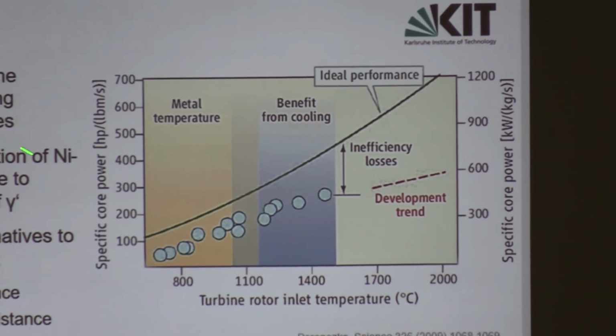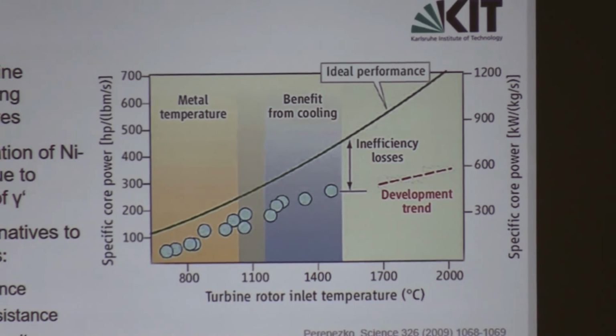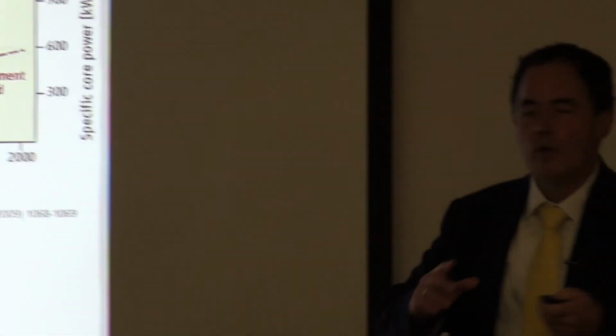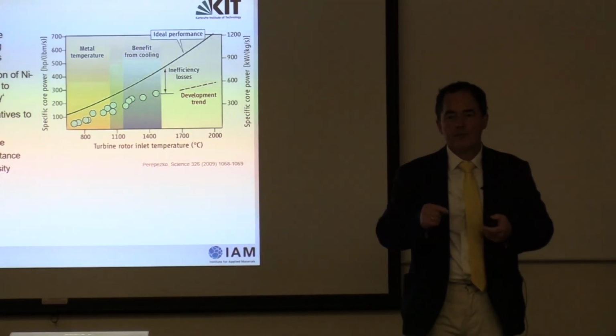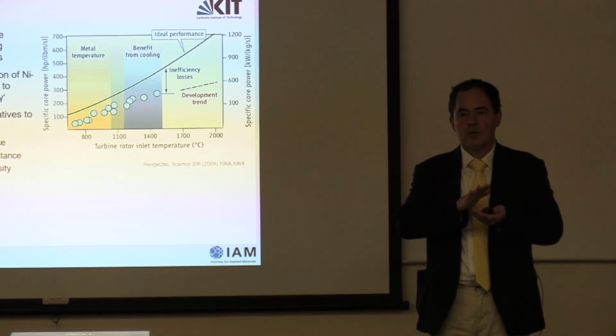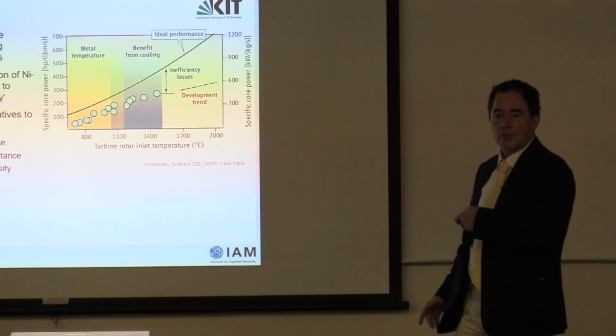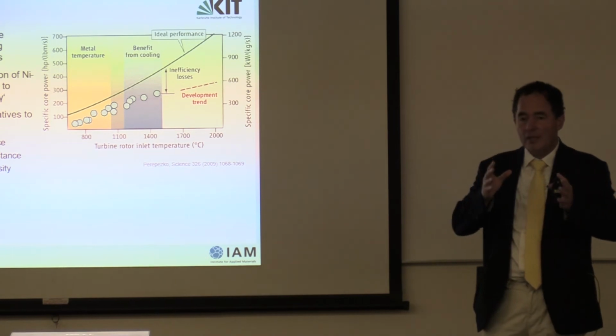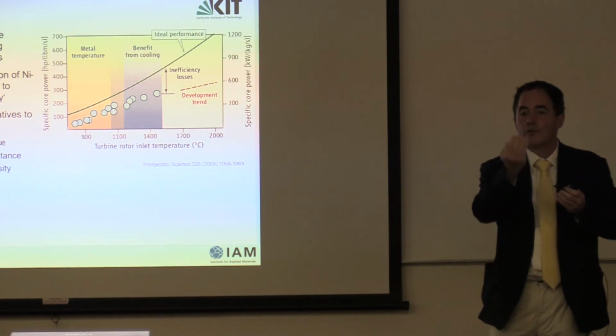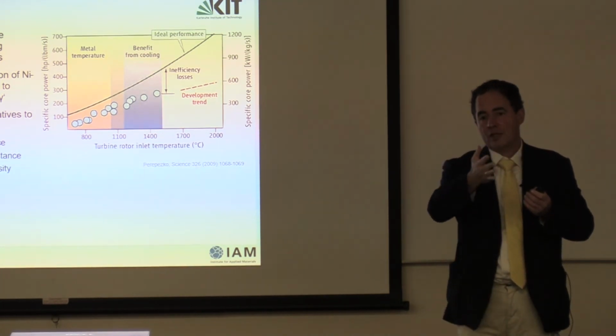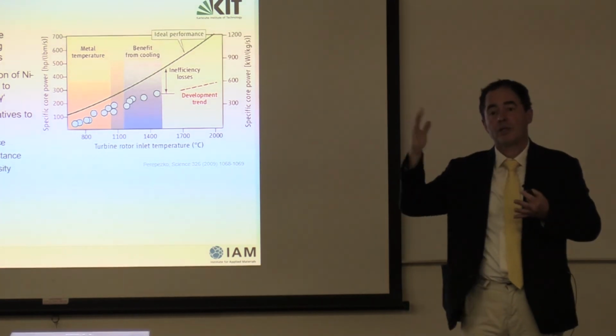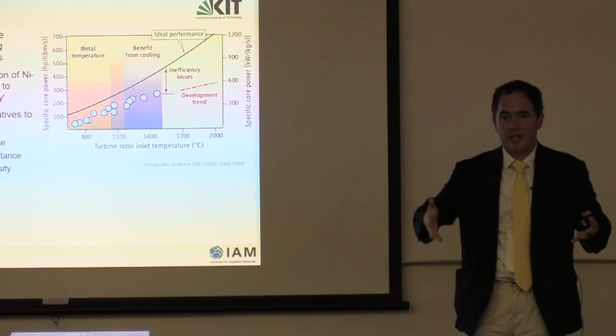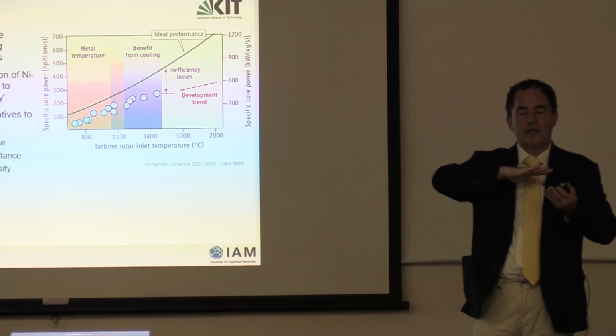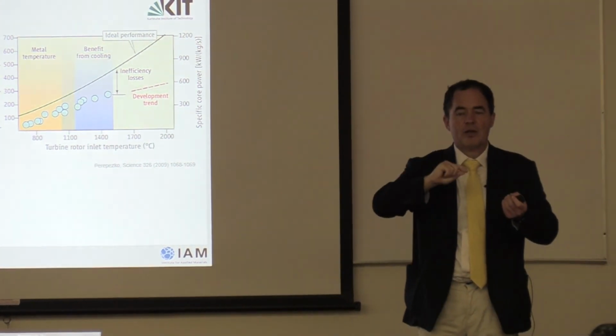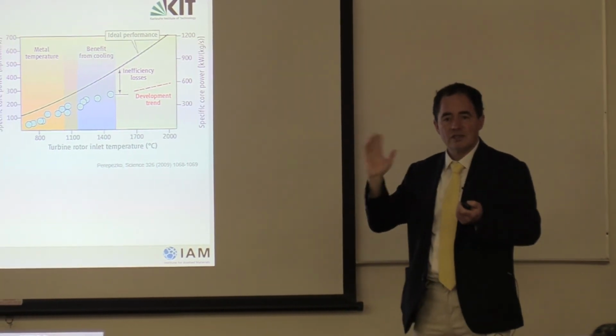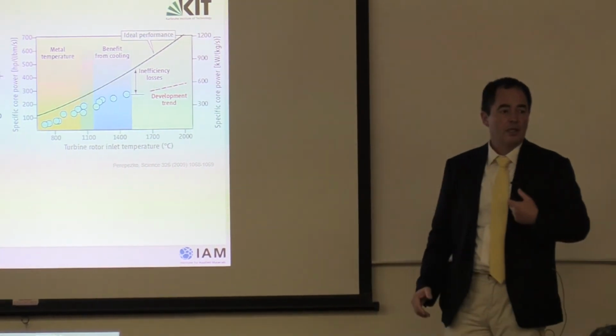And what I also did not tell is, why is this deviating even more from this ideal performance? The reason is simply that now, for this rotor temperature, you have to apply an environmental barrier coating on the metal surface. These are no longer uncooled blades. These blades are really made in a very tricky way. They have cooling holes, they are cooled from the inside to get film cooling on the surface, and they are protected by an environmental and a thermal barrier coating. The environmental barrier coating protects against oxidation attack, and the thermal barrier coating reduces the temperature of the metal blade, but both come along with a disadvantage in efficiency, or with an increase in inefficiency losses.